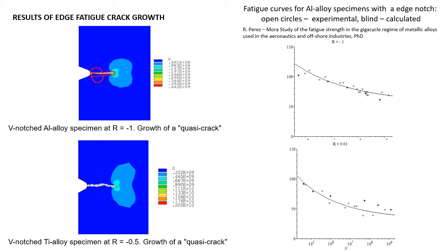The total fatigue life was calculated based on 2 steps. The first step is initiation and early growth, and then propagation in high cycle fatigue. The results of the fatigue life for such a specimen are presented in the figure on the right. The open circles correspond to the experimental data, and the solid points are calculated results. As we can see, we have a good agreement between the experimental and numerical simulations.